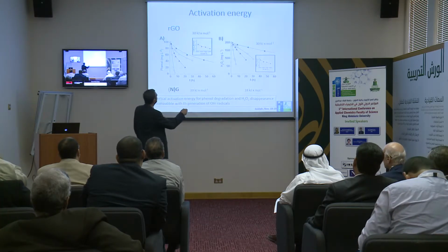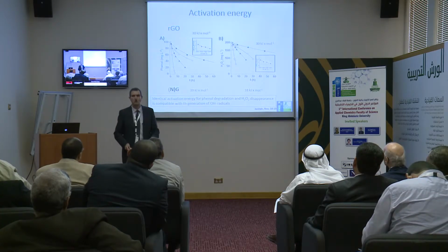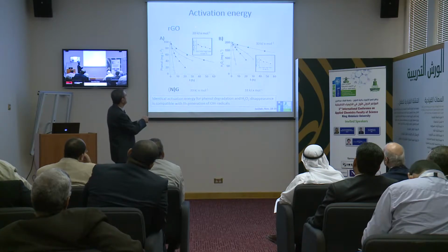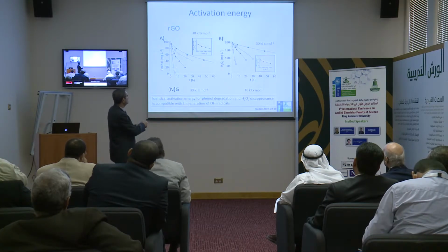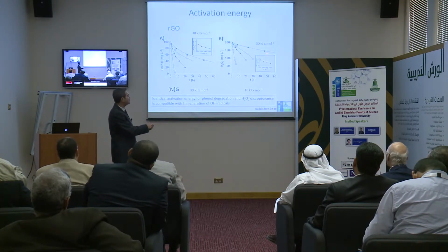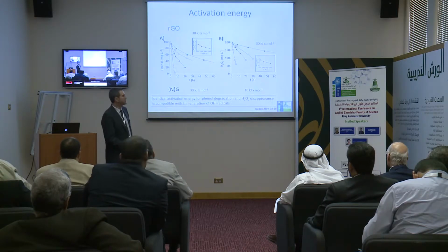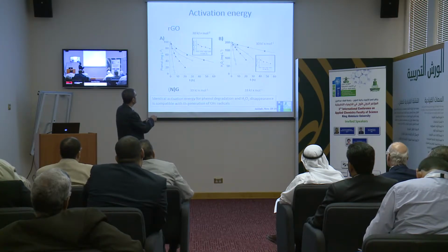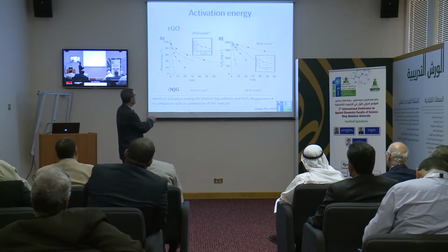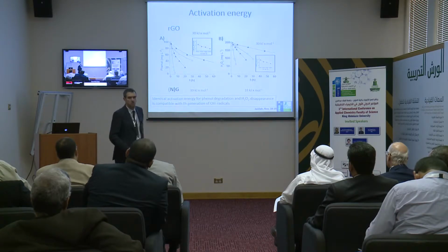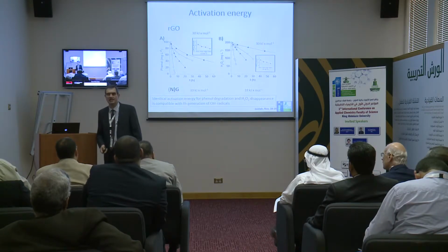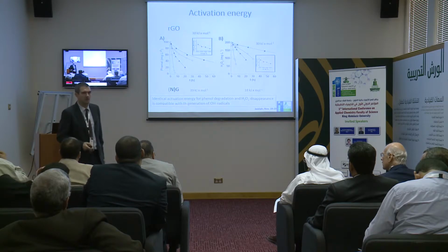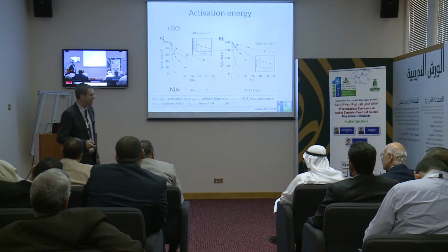Activation energy. One thing that is important in a very good Fenton catalyst is that the activation energy for phenol degradation and hydrogen peroxide decomposition should be the same. And here is the conclusion. This is the activation energy for phenol decomposition and hydrogen peroxide, and it coincides. So this means that really this catalyst is very good for Fenton reaction in the absence of any metal.